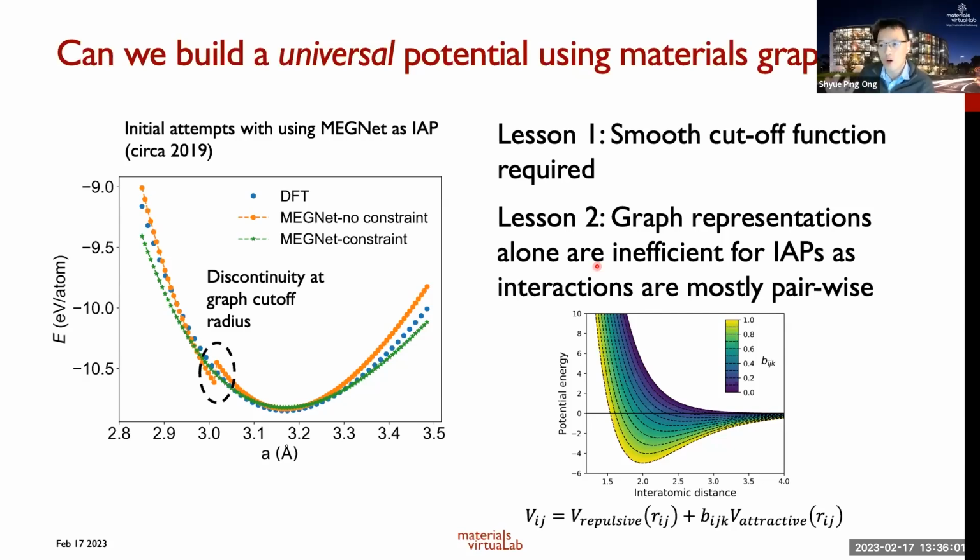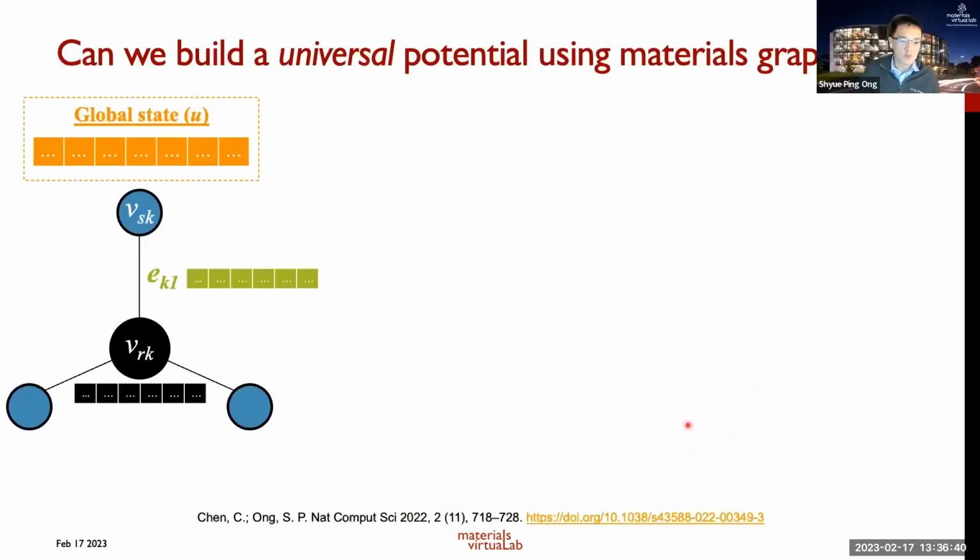So, of course, with more layers, you can actually get something close to multi-body interaction terms, but that message passing is not a very efficient way of representing multi-body interactions, right? And in most systems, multi-body interactions are actually critical in getting a good interatomic potential. So what we did was take some inspiration from the traditional interatomic potentials, like the Tersoff potentials, where essentially you augment the materials graph with some form of n-body interaction, okay? So this is basically what we did.